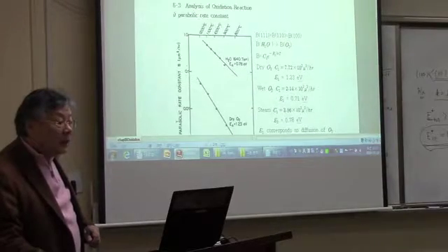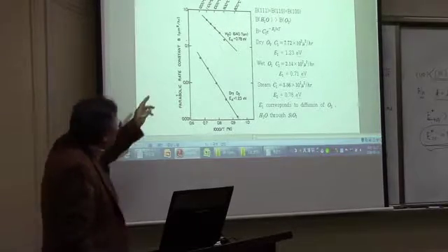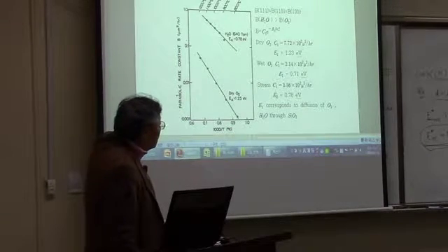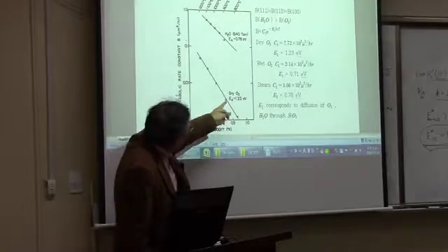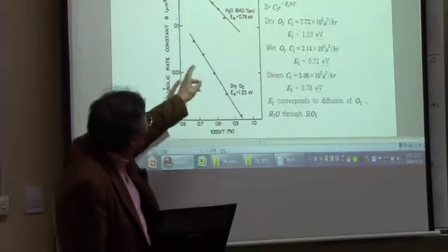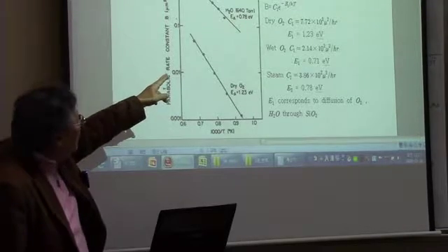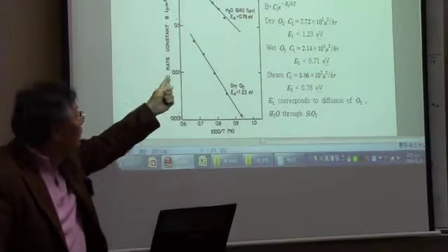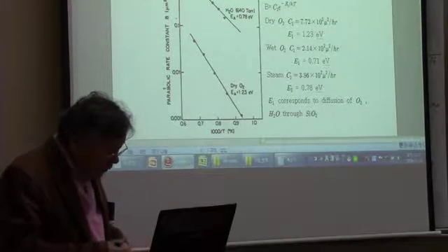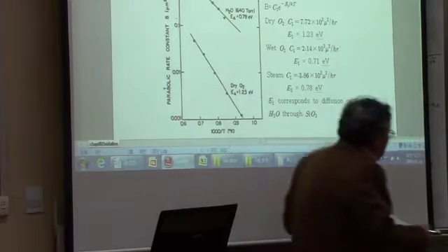Okay, and the next figure is about the parabolic rate constant. Parabolic rate constant is constant B in the discussion that we have made. And you can see in the dry oxidation the activation energy is 1.23, and the activation energy for the parabolic rate constant in case of H2O is about 0.78. It's much lower. So in this figure, we can arrange things something like this. Okay.